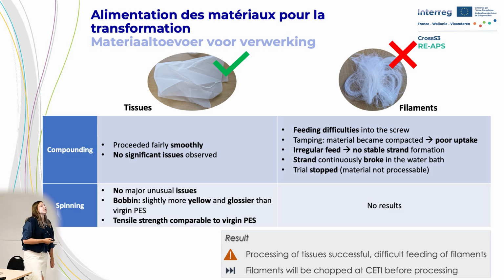Then when we went on with filaments, we had feeding difficulties into the screw. By tamping, the material became compacted, and this leads to a poor uptake by the screw. So we had an irregular feed and no stable strand formation, as the strand continuously broke in the water bath. We had to stop the trial, and it's not processable in this way. The conclusion is that processing of tissues was fine, while feeding of filaments was difficult. To overcome this challenge in the Re-APS project, we decided to cut the filaments before processing.